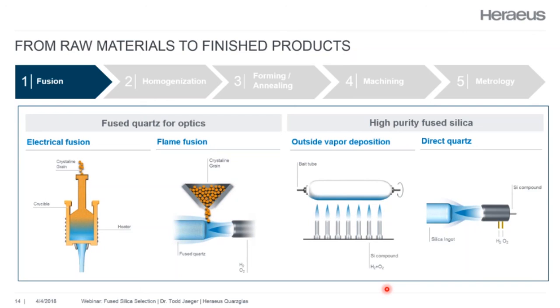One is OVD, or outside vapor deposition, and the other is direct quartz. Instead of using a solid precursor, we use a silicon-containing gas. This gas then is burned within one of these flames in a hydrogen and oxygen environment. In the OVD process, we have a tube or a target that's rotating, and we build up a soot, which is really a silicon dioxide, but it's a lower density than what the final fused silica would be. This soot body, as we refer to it, is then taken through another process at very high temperature, where the vitrification and the formation of fused silica actually occurs. Alternatively, direct quartz is just what it states, and this is where we would still have a silicon-containing chemical compound that goes through the flame hydrolysis, but this hits a target, and the target is moved away slowly, which allows you to build up layers of fused silica.